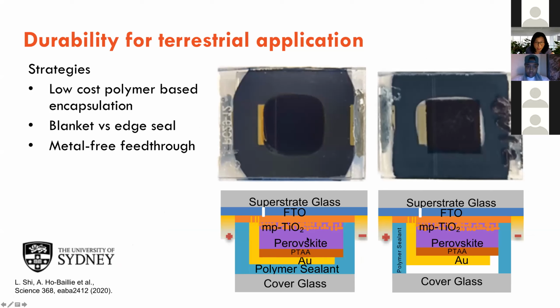If you protect the solar cell and you protect it well, and you put it through the GCMS, you shouldn't be able to see those signature products. But if it's not protected well, you will be able to see those signature products. In this case, we use a very low cost way of encapsulating the cell using materials, for example, PIB, polyisobutylene, or polyolefin, that's used for laminating two pieces of glass in the industry.